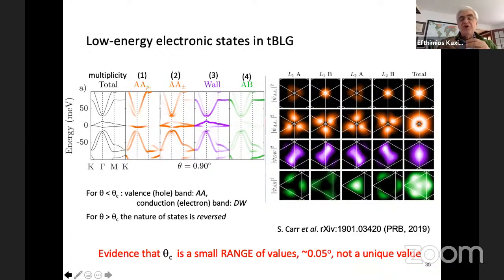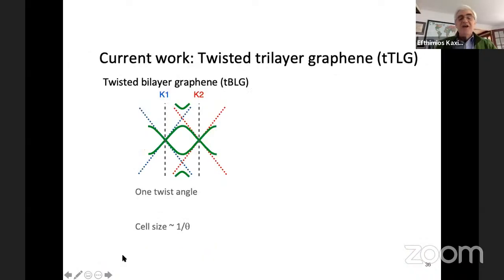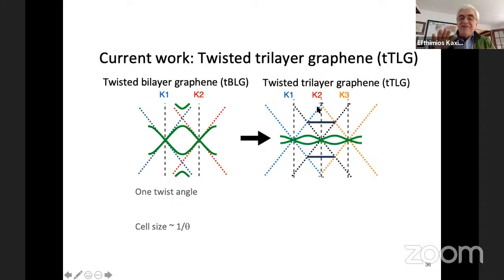So instead, I'm going to show you something very recent and even more complicated and potentially even more exciting. So this is the picture that I showed you about the bilayer graphene, the two Dirac cones, coming from layer one and layer two, and the bands splitting here, repelling each other, with the cones splitting at the intersection and forming the flat bands. And now here's what you would have if you have three layers of graphene stacked on top of each other. So you have three different Dirac cones now, all of them again interacting. And at these points where the bands meet, where they intersect, they would form again split bands.